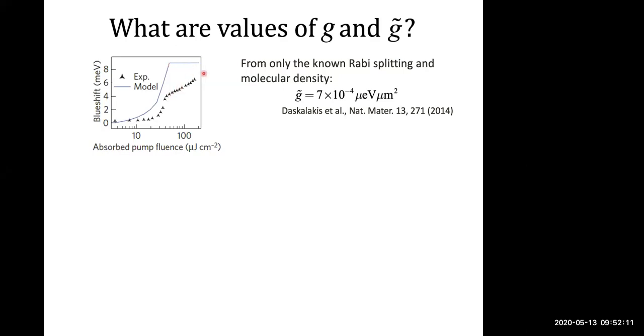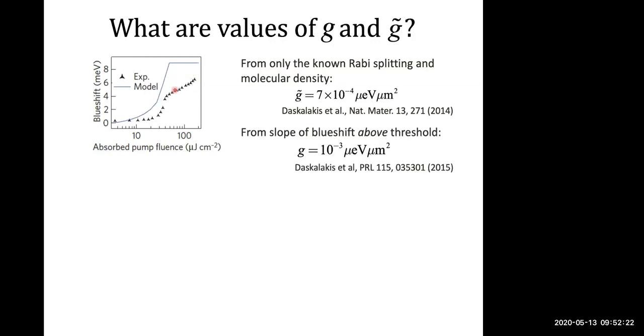And in this beyond threshold part, the blue shift is due to polariton-polariton interactions. So from the experimental data, you can also get the G value, and we find from the blue shift above threshold that G is on the order of about 10 to the minus 3 micro eV micron squared. So to put this in context, this is almost 3 orders of magnitude lower than the blue shift in gallium arsenide. Okay, so this is problematic if you want to reach a regime such as, for example, the polariton blockade regime.